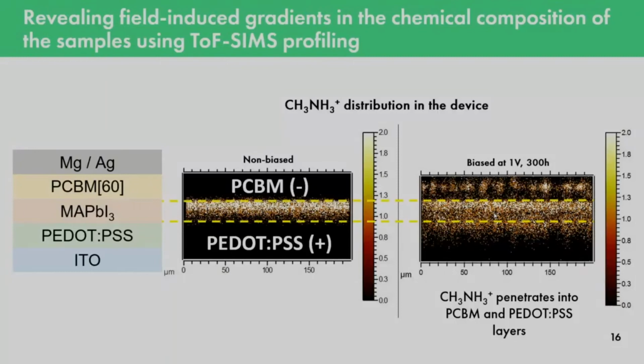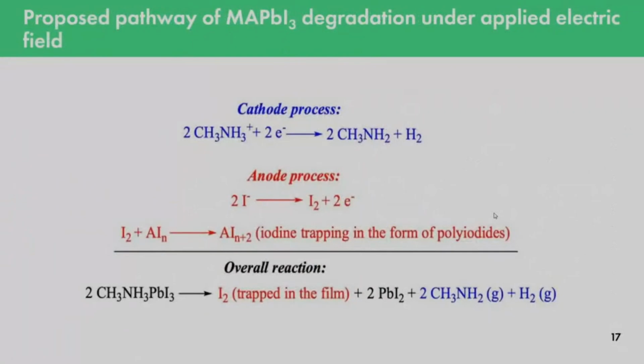And the appearance of this kind of cations in PCBM can be explained by simple ion migration, because PCBM is on the cathode part, but the penetration of methyl into PEDOT:PSS can be explained only by the fact that we have some products of electrochemical reduction of methylammonium cations, which react chemically with probably polystyrene sulfonic acid, which is a component of the PEDOT:PSS material.